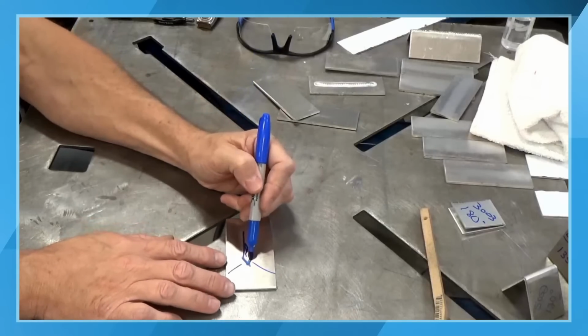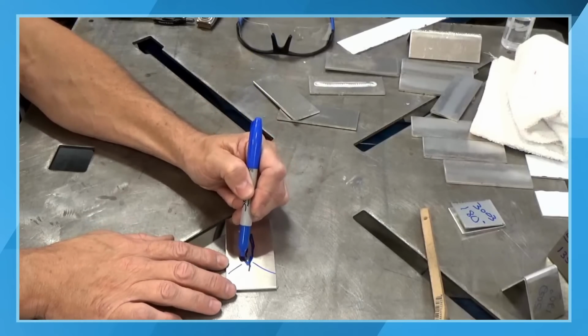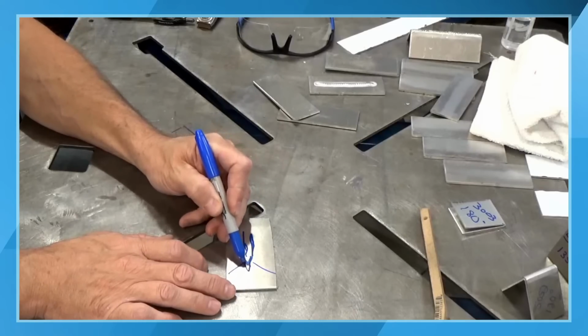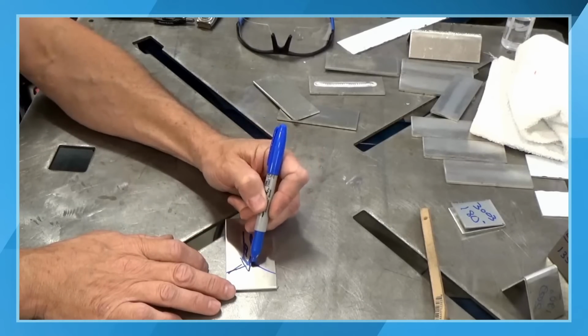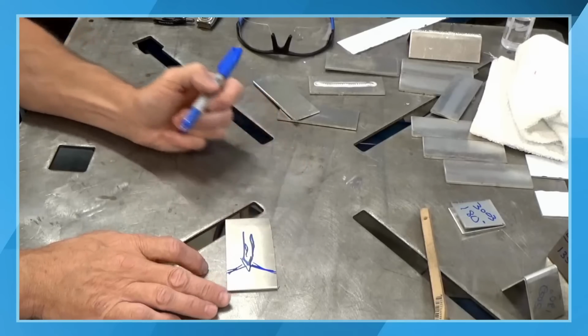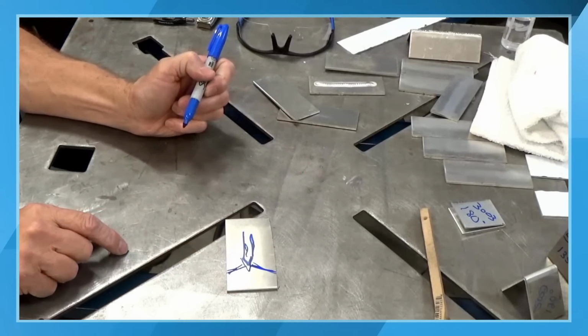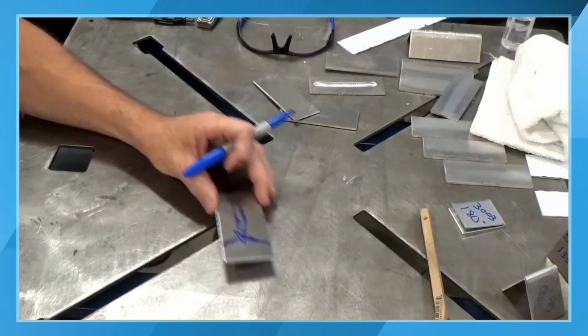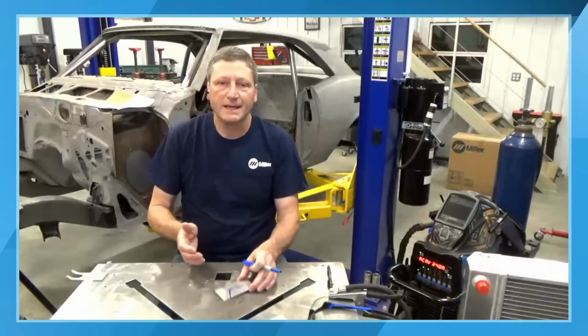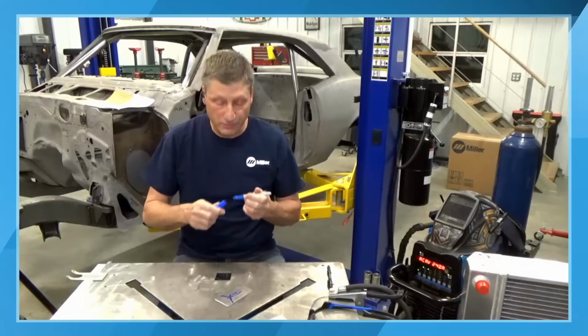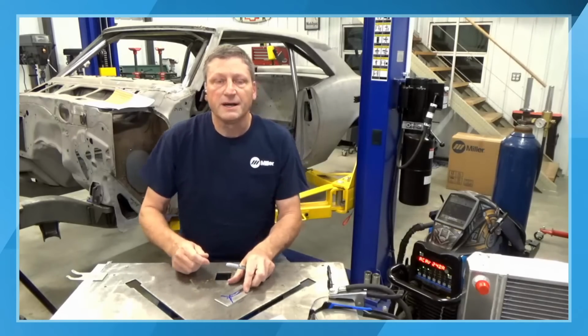Okay? If you put a longer taper on here, the arc tends to start to jump off the tungsten roughly at a 90 degree to the grind. So you're actually making your weld puddle wider. And so I grind at roughly a 30-degree grind for most of my stuff.